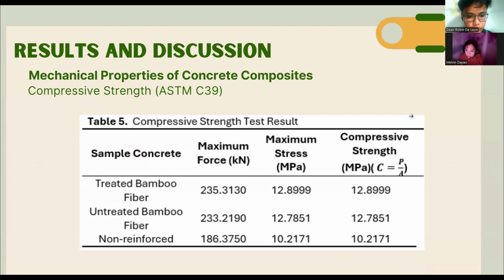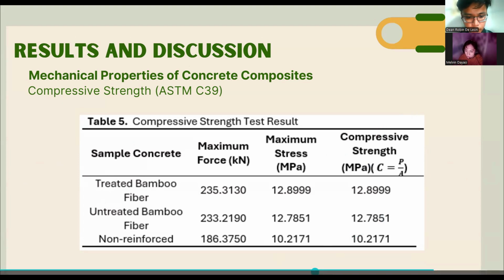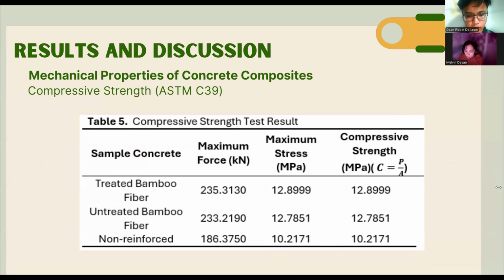And for the compressive strength, treated bamboo fiber reinforced concrete exhibited the highest performance with a maximum force of 235.3 kilonewton, a maximum stress of 12.89 megapascals, and a calculated compressive strength of 12.89 megapascals. Compared to untreated fiber reinforced concrete, the treated fiber reinforced concrete showed a slight 0.9% increase in compressive strength, with a compressive strength of 12.78 megapascals. It also demonstrated a significant 26.2% increase compared to non-reinforced concrete, which had a compressive strength of 10.21 megapascals.